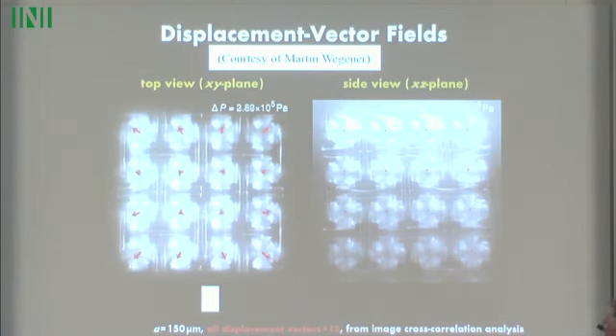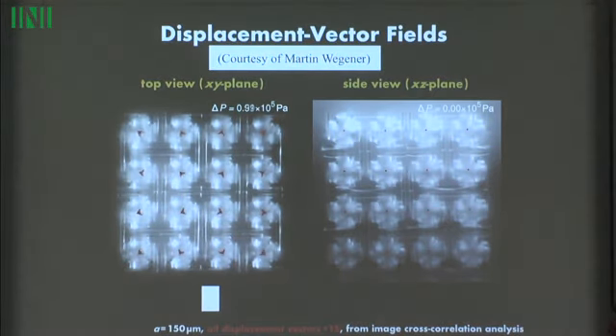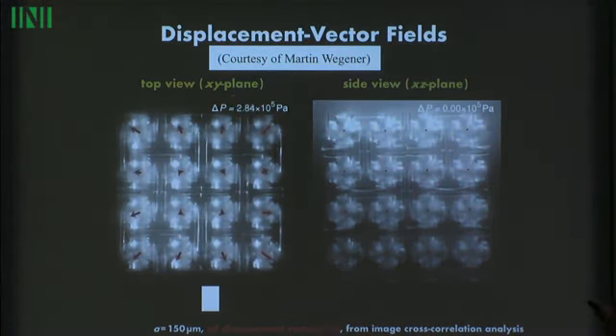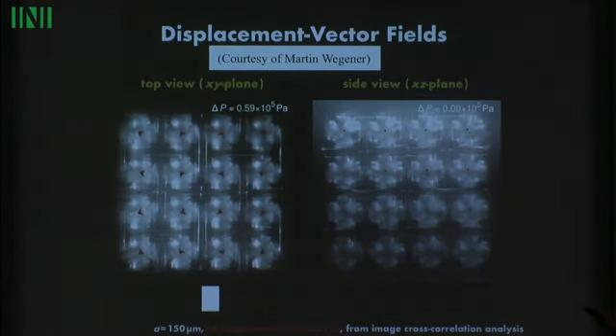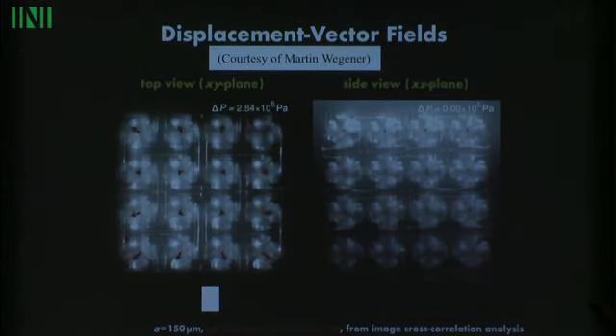So this is the pressure here. This is, if you like, a structure all underwater. If I had an air-filled balloon and put it underwater, and I increased the pressure in the water, the balloon would shrink. This actually has the complete opposite behavior. You increase the pressure in the surrounding fluid, and the structure actually expands. And the side view shows basically the same.